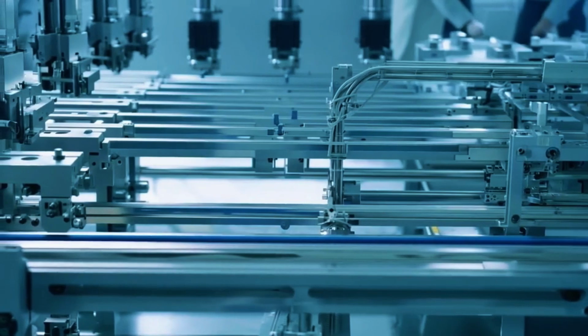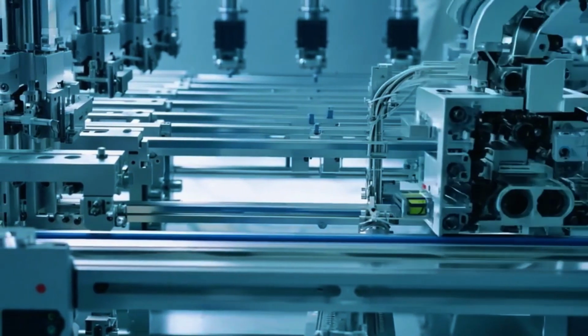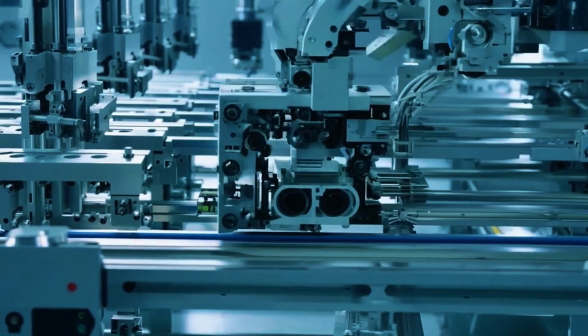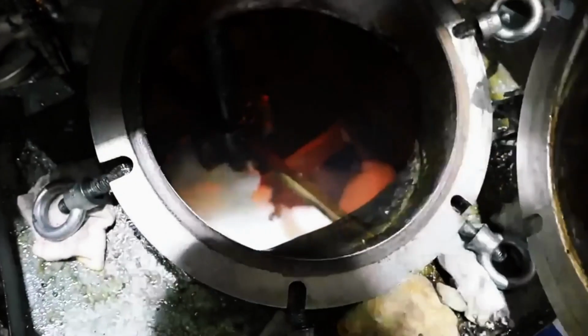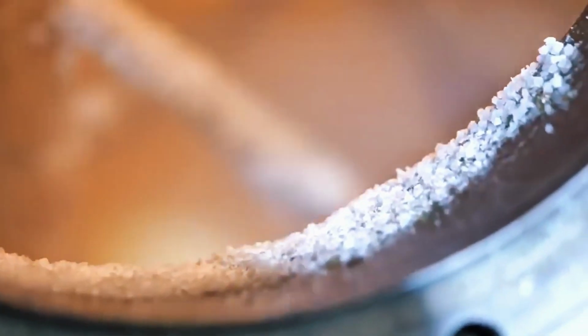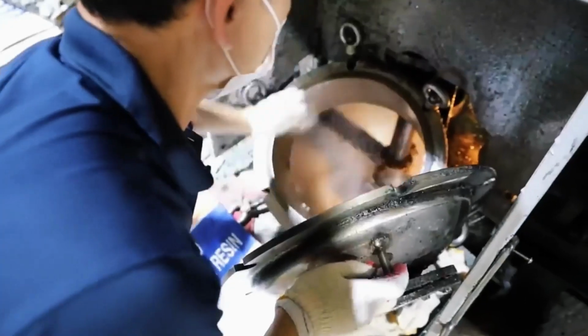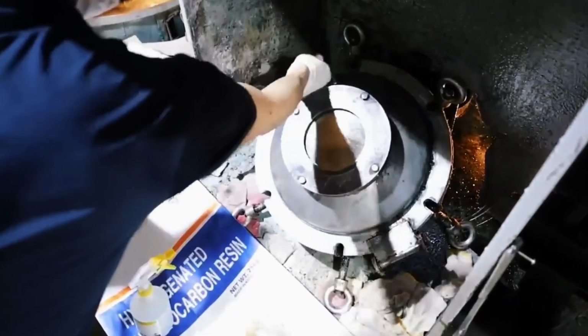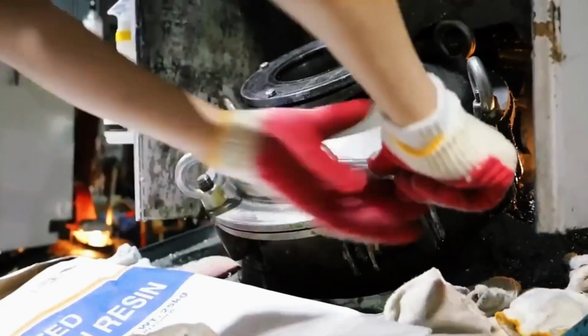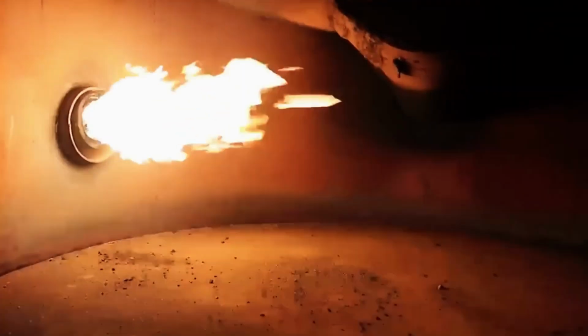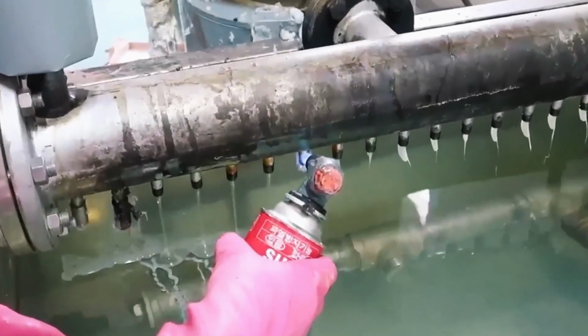With the monomers obtained, the stabilization stage begins, arguably the most delicate part of the entire process. These monomers are so sensitive that a single breath of humid air is enough to trigger immediate polymerization. If left unchecked, the glue would harden before ever reaching the consumer. To prevent this, chemical inhibitors are added in microscopic quantities, measured in parts per million. Hydroquinone neutralizes free radicals, while acids such as phosphoric or sulfonic keep the environment acidic, blocking the action of basic ions that could start the reaction. The method is comparable to seasoning a giant stew. Just a pinch at the exact moment makes all the difference.